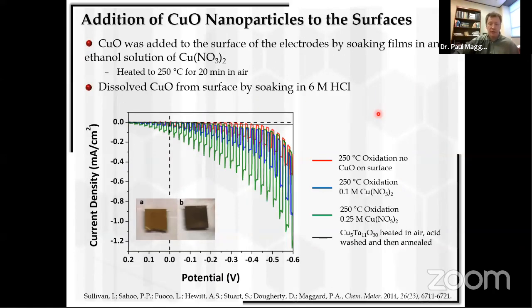You can do the same thing, though, not by oxidizing the particles, but by making the nanoparticles of copper 2+ oxide, and then just depositing them onto the surface. And so we've taken the same films, made nanoparticles of cupric oxide, and deposited onto the surface. And again, we see those very high photocurrents occurring, which tells us that they're critical for that activity, right? That while that material can absorb the visible light, the bare surfaces are not catalytically active by themselves.